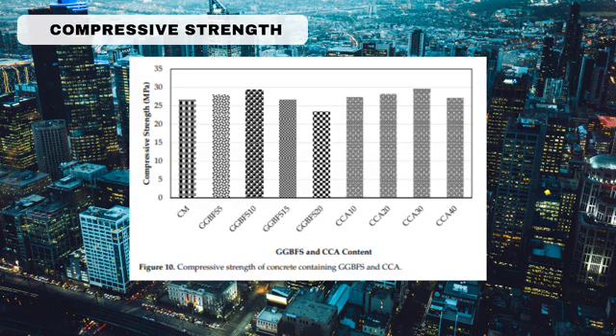The concrete mixture is blended with GGBFS as a PC replacement and CCA as a FA replacement, analyzing the compressive strength at 28 days. The peak compressive strength is 29.40 MPa with 10% GGBFS as a PC replacement and 29.58 MPa with 30% CCA as an FA replacement at 28 days. Similarly, the lowest compressive strength is 23.50 MPa with 20% GGBFS as a PC replacement and 27.18 MPa with 40% of fine aggregate replaced with CCA at 28 days. The compressive strength is heightened with 10% GGBFS and 30% CCA.